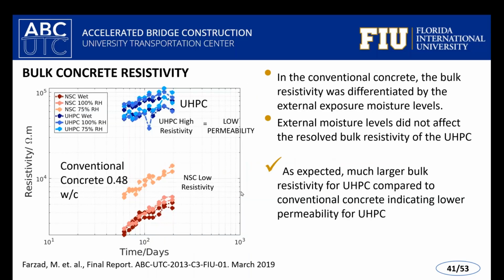So how can UHPC be beneficial to us for these types of problems? Here are results that were conducted at FIU a handful of years ago, but very pertinent, just exploring some of the generic characteristics of UHPC, and one is the electrical resistivity of concrete. So even for conventional concrete, we use this as a means to identify quality of the concrete and conditions where corrosion may occur. So resistivity is related to permeability. It also relates to possible coupling of these anodes and cathodes that is required for corrosion to occur.